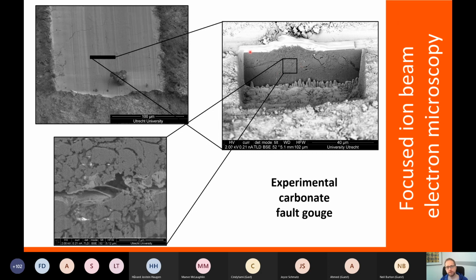And for this, we cut a trench into the front using the focused ion beam scanning electron microscope, and then actually had a look from the side. So you not only now can image the surface here, but you can also see what's happening below the surface. So you get a better three-dimensional impression. And you see here, typically these trenches are on the order of several tens of micrometers. The larger you make them, the longer it takes with a standard gallium ion beam source.